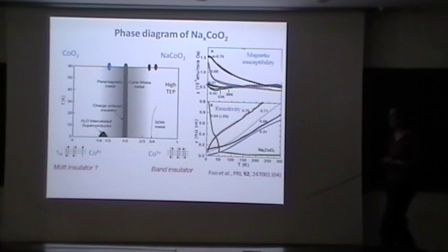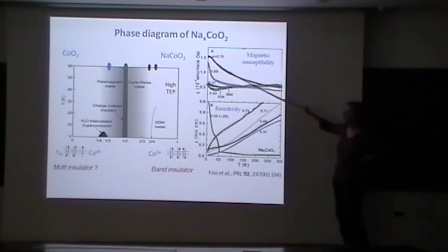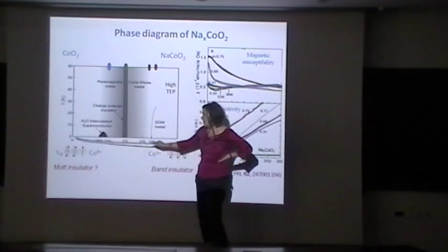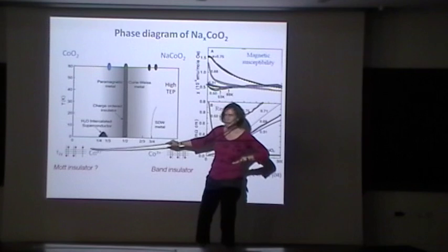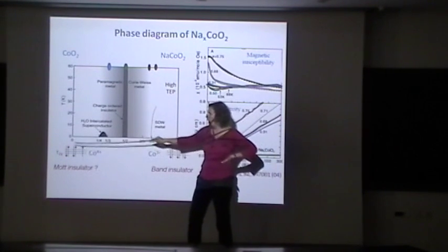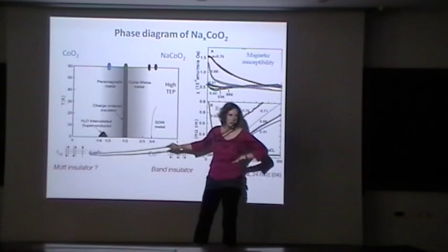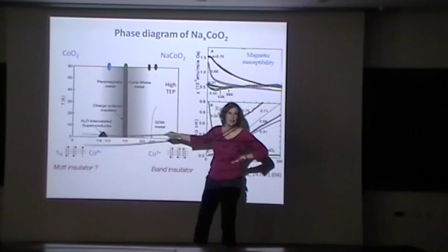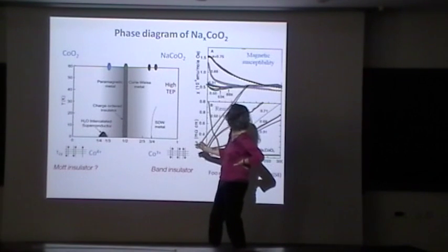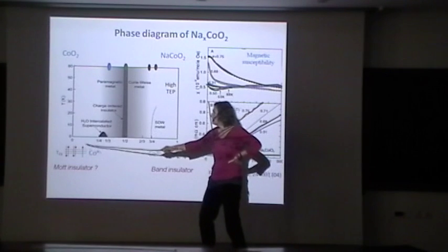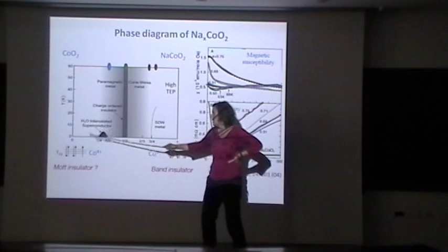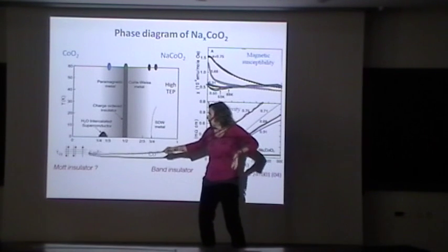But what is surprising here is that you would really understand that you have this strong magnetic correlation where you are near these states here, where all cobalt sites have spin 1/2, and so you're very near these states, which could be a Mott insulator, and where you could expect that you have strong magnetic correlation on this triangular lattice that is frustrated and so on. But in this part of the phase diagram, you see no evidence for these spin correlations, and it's really when you go up to here, where you don't have so many spin 1/2 left, and where correlation